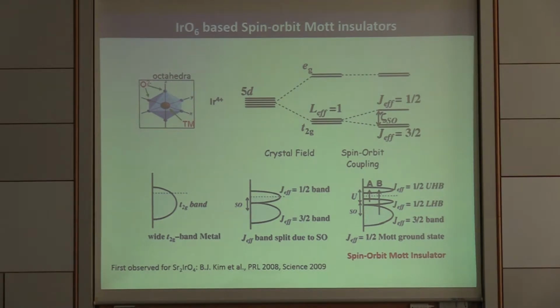So as an example, I consider iridium oxides where we have iridium in a 4 plus valence state, meaning that we have 5 electrons in the 5d shell, and in the octahedral crystal field we would have, ignoring spin-orbit coupling for a moment, t2g states which are filled by 5 electrons. So given the large spatial extension of the 5d shell, we would have expected a metallic state with 1 hole in the t2g band. And it came as a big surprise that, for instance, the layered Sr2IrO4 is actually an insulator, while the isoelectronic ruthenium material is a well-known metal and superconductor.